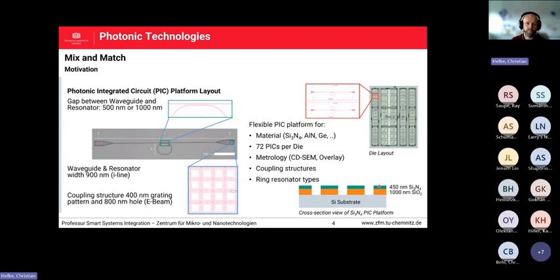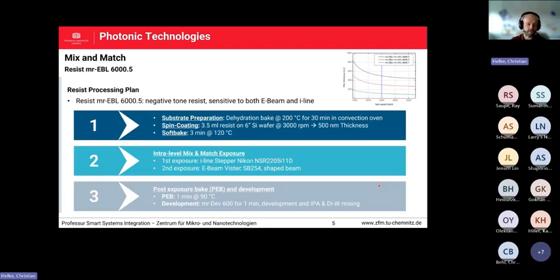So the resist, which is needed for dealing with the mix and match lithography approach, has to be a resist which is sensitive to E-beam, to electrons, and to I-line, to photons, for example. And we use for this case from microresist technologies the mr-EBL 6000.5, which is an amplified negative tone resist, which can be exposed with the E-beam and the I-line, for example.